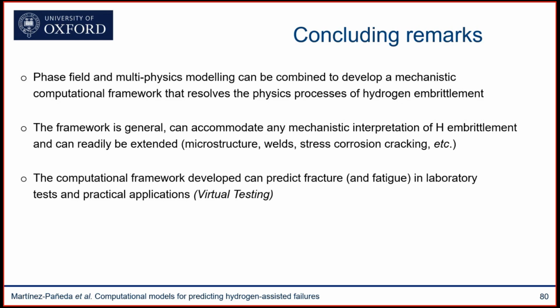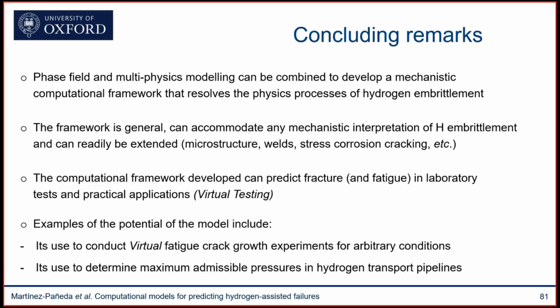So it can capture, as I said, in a physically based manner, not only fracture and fatigue experiments in the lab, but also can handle the very complex conditions and large scales inherent to engineering practice, effectively bringing this virtual testing paradigm to hydrogen-containing environments. And I think there are multiple things that you can do with this model, but the two case studies that I wanted to show today: one was that we could do virtual fatigue crack growth experiments for arbitrary conditions.